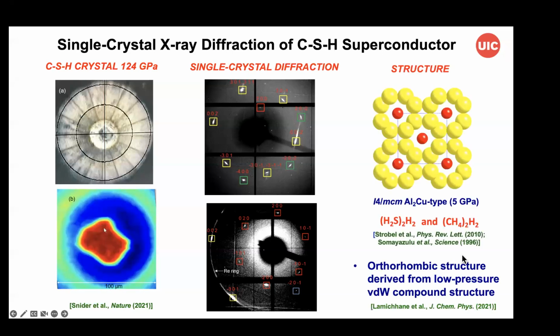And from this, we're able to show that these are continuous with the structures that we found earlier in the isolated systems, the H2S-H2, and the CH4-H2 system. So this provides a way of understanding how this mixing of carbon and sulfur can result in some kind of phase that has carbon, sulfur, and hydrogen at higher pressure.